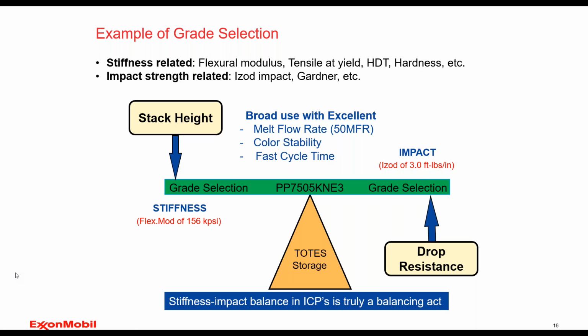And then if you're concerned about the stack falling over, you don't want a disappointed customer with a bunch of broken parts. So drop resistance or drop impact is important. This is very recognizable to most of us when we have gone into stores to even look at storage bins. The random copolymer offers that clarity, but can't get close to this level of impact resistance that an ICP has. And usually when you look at a stack of totes, you'll see cracks at the bottom edges of those random copolymer totes. Nicole, if you give one more click there.